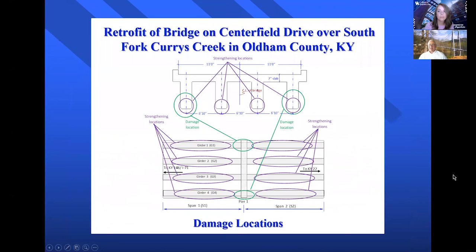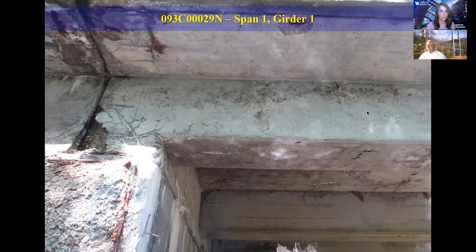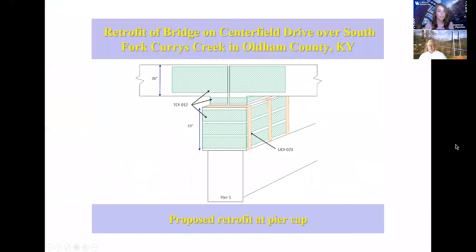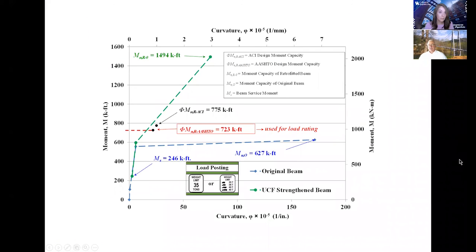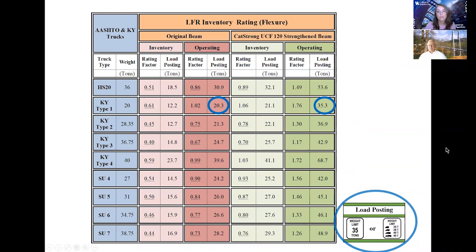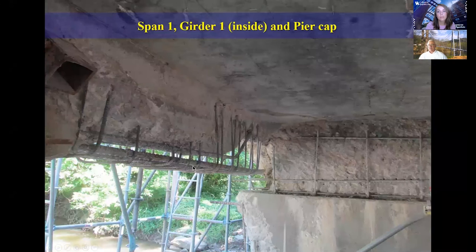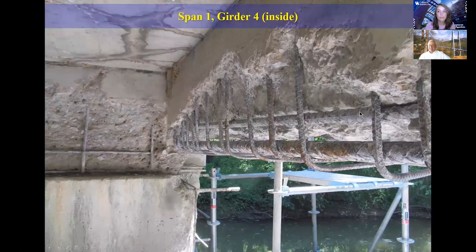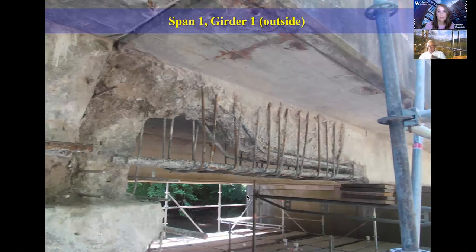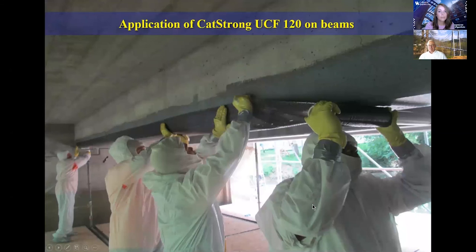This is another bridge I'm going to take you through. The bridge looks innocent and the damage is not that bad, but once you start removing the bad concrete, in this one, we were not done yet. We removed almost this entire portion of the concrete of these beams and also over the pier cap. So if you don't do that, there's really no purpose of putting the carbon fabric in there. It would not have. So you have to remove this entire bad concrete.